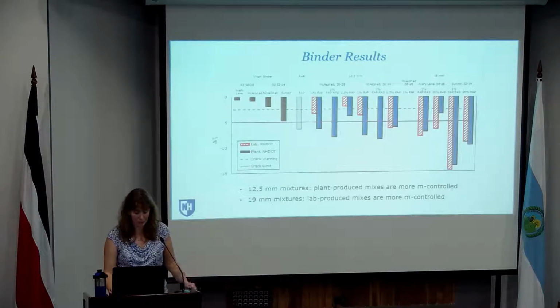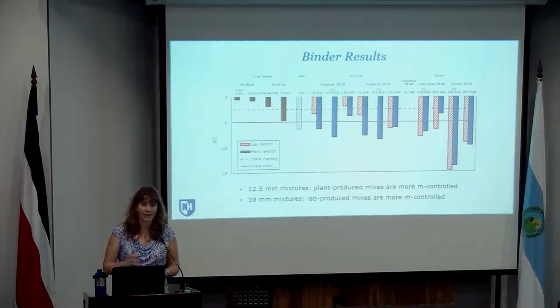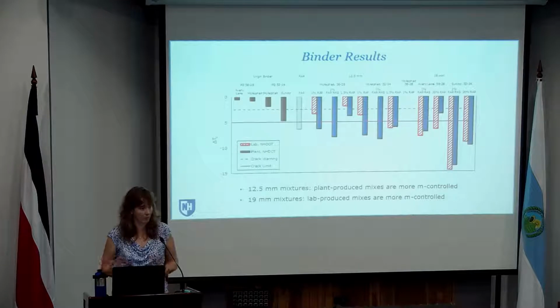Okay? And again, we're seeing differences between the lab and the plant. In this case, the lab aging didn't have as significant an impact on the delta Tc as the plant aging. Okay, so they're different in terms of the PG grades versus where you're seeing the differences in the stiffness and the relaxation capacity. So that was important to note. So those are the binder results.